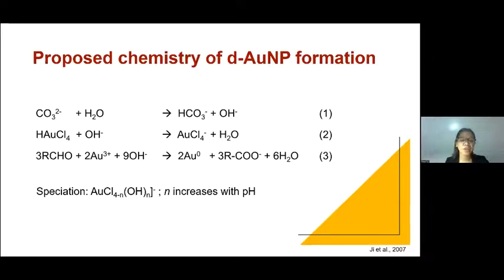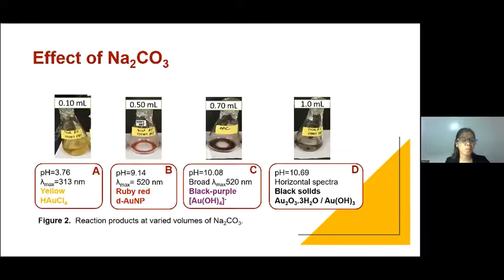The increase in the temperature is necessary for the chloroauric acid-dextrin system because while dextrin can undergo oxidation under basic medium, the increase in the pH drives the speciation of chloroauric acid to its gold complexes. In the present study, stable red gold nanoparticles were produced from the reaction mixture with sufficient amount of OH- for both neutralization and alkaline reduction.